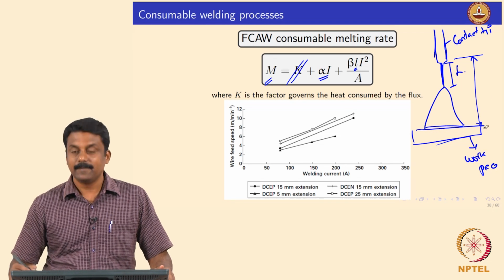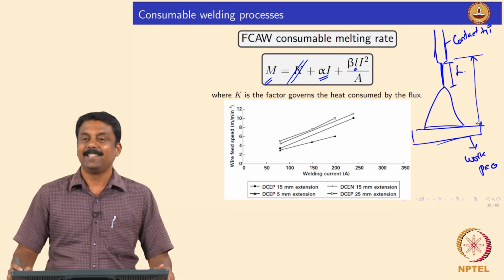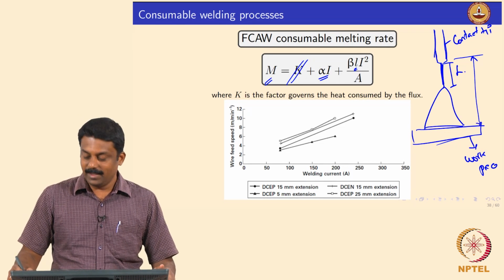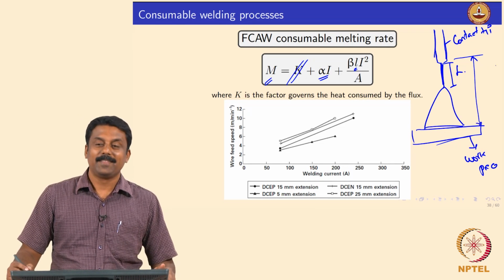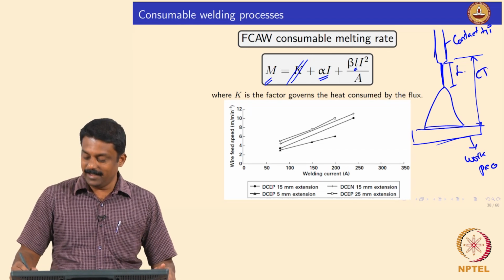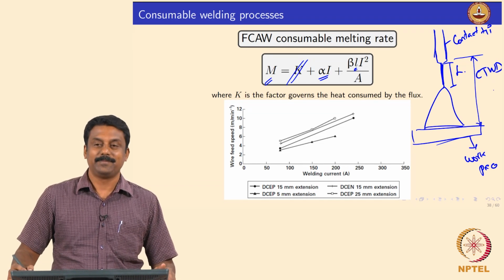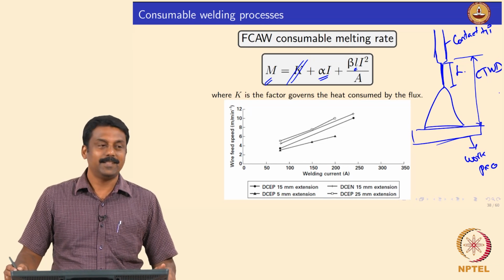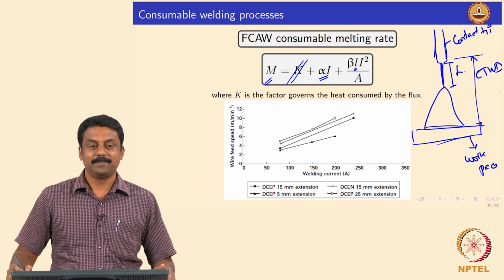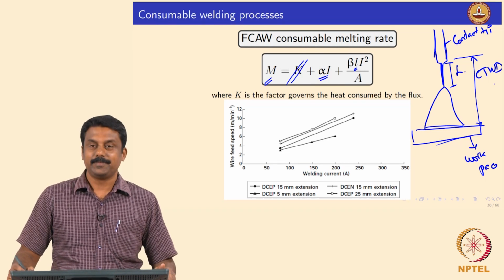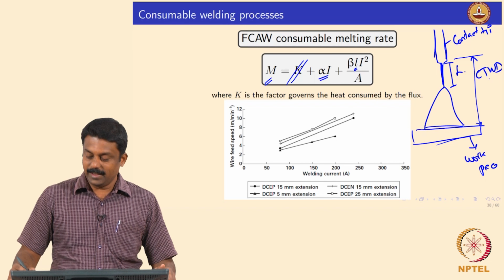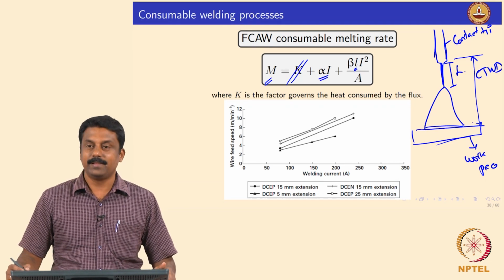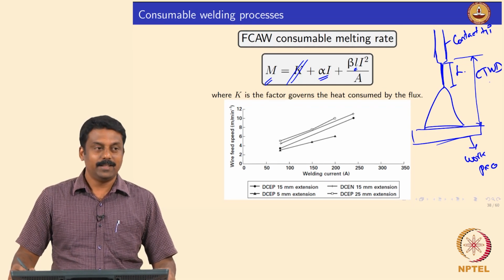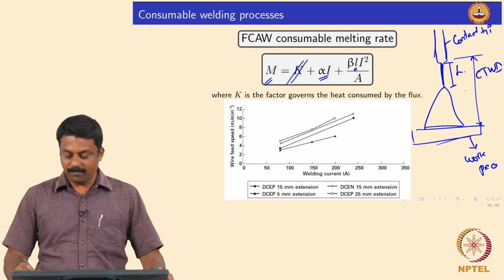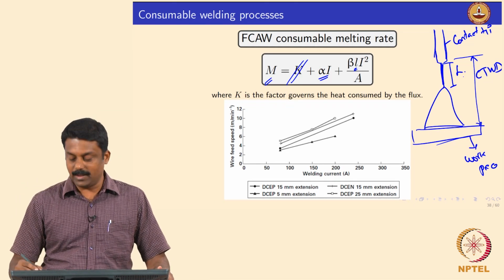Then what is this distance? This is contact tip to workpiece distance. Okay, it is very simple. So, CTWD, that is what we define all the time. CTWD minus arc length is your stick out length, right. So, CTWD defines the distance between the contact tip to the workpiece, and that is a very important parameter, right. So, CTWD is an important parameter, because that would determine the stick out length and the arc length.